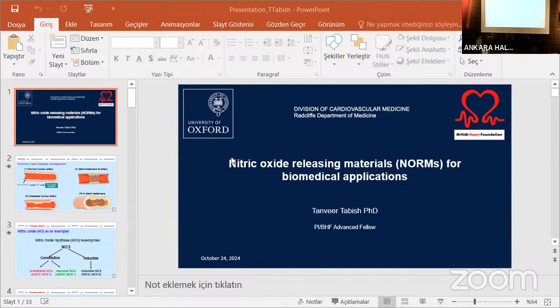to stent materials, and then because these are polymer-based stents, we also want to show that they are biodegradable. So if we do the accelerated degradation conditions, high temperature, we see that up to 60 days there is a huge weight loss in the material. That's what we want to achieve, because generally when you use stents, you have to take them out after 2 to 3 years. But if you have a biodegradable stent, it will be degraded and disintegrated into smaller size particles and will be cleared from the body.